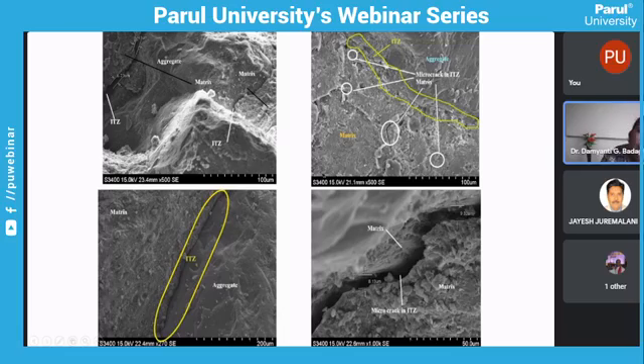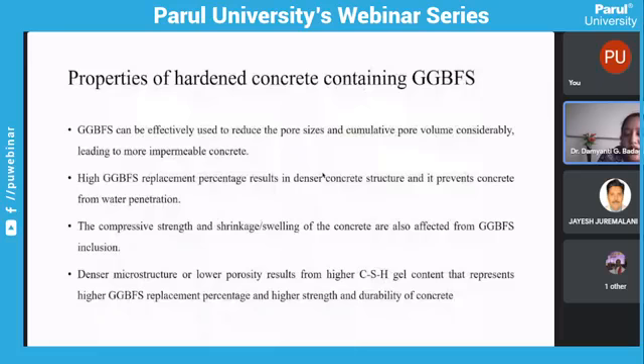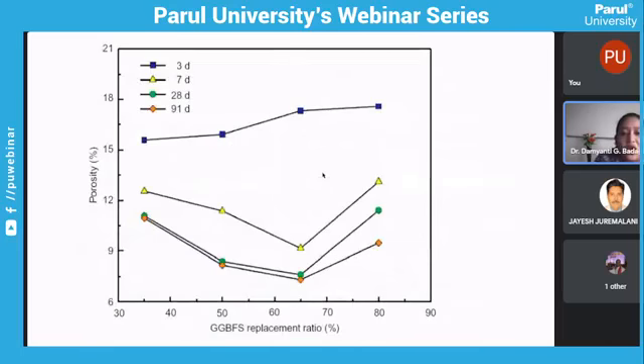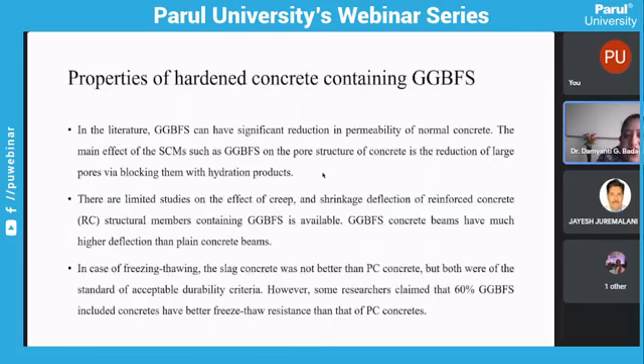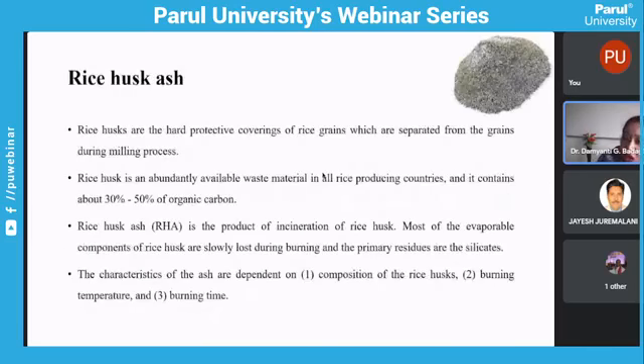Okay. So from those SEM images, we can see there is a good bond between the matrix. Matrix means your cement, aggregate, and water, right? So there is a good bond between the matrix when we are using 50% GGBFS as cement replacement. And as I told you, its hardening properties are good. Here you can see the result of porosity with GGBFS replacement. And as I discussed, whenever we are preparing concrete with GGBFS, its properties are definitely good.